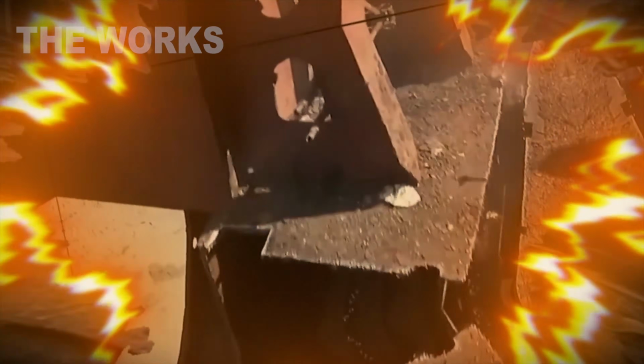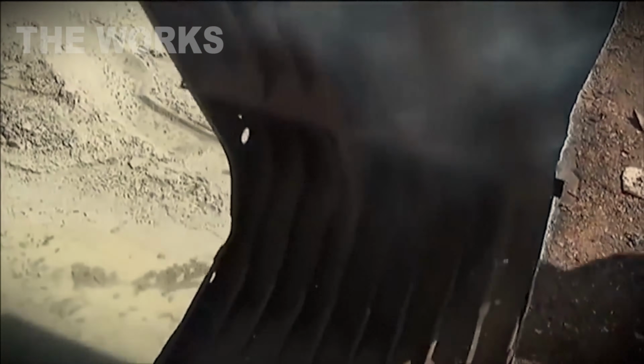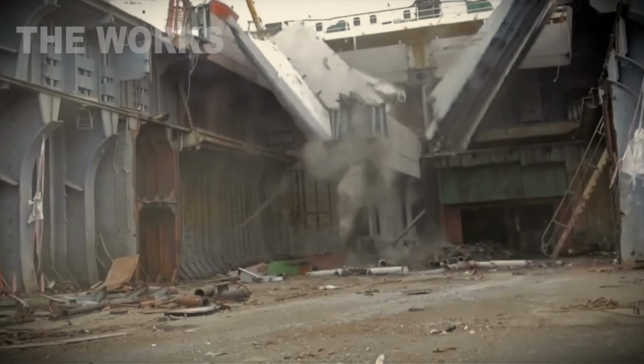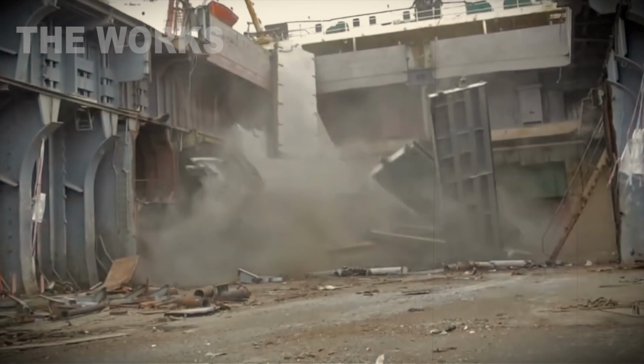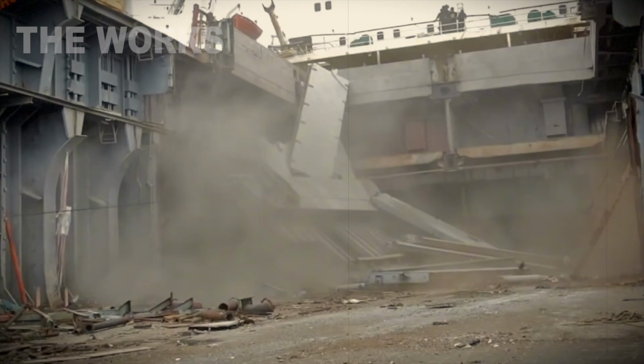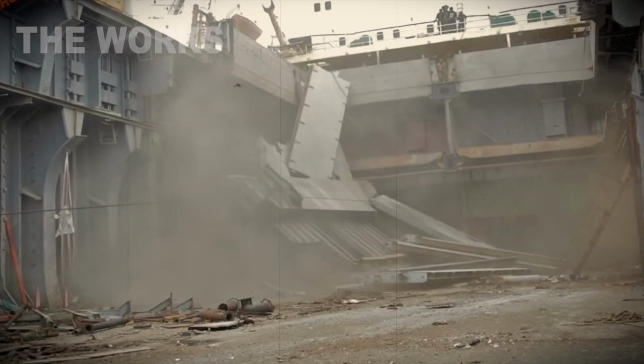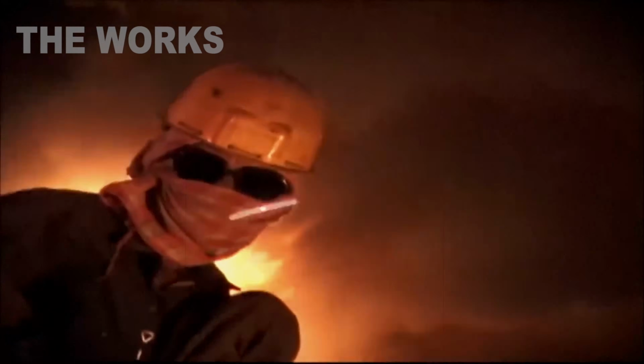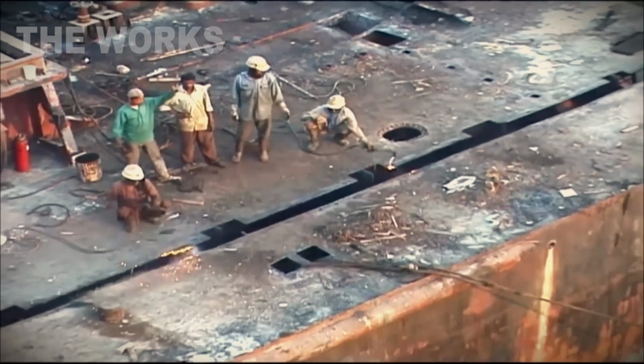Metal sorting. Every hull fragment gets checked again with dosimeters. They're hunting for isotope traces in microcracks and weld seams. If the device clicks, the fragment gets isolated, sent for recleaning or special disposal. Only clean metal receives a safety certificate. It can leave the shipyard territory, then sorting by chemical composition.